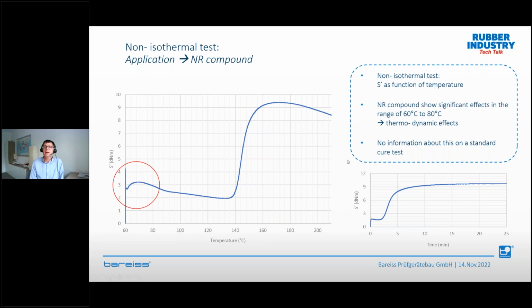This is something like thermodynamic effects that you see here, and that will definitely have an impact on the mixing behavior of your compound. This happens sometimes with natural rubber compounds. It is less with natural rubber when you have constant viscosity types, but with SMR you see this type of effect very often, which is sometimes present in the process and sometimes not. But again, this gives you this additional information when you run a non-isothermal test instead of only an isothermal test.